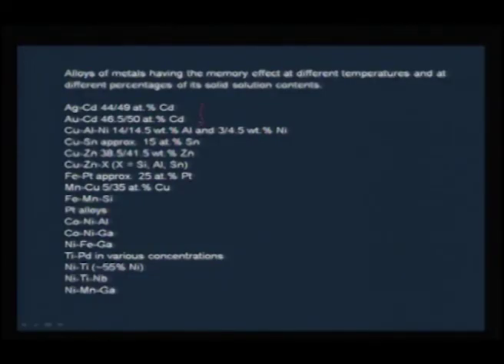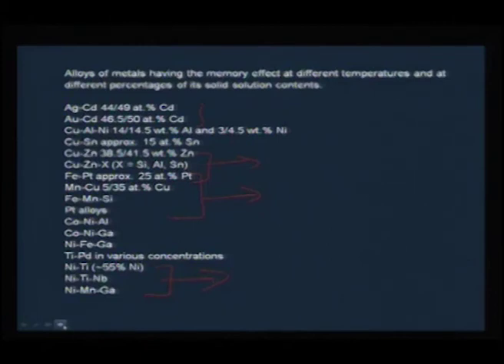Some show only one way, some show two way shape memory effect. So, we have a list of alloys which have been used. In the initial days of discovery, actually in the previous century, it was silver and gold based ones which have shown such a shape memory effect. But what we see now is predominantly the titanium nickel based one, which is nitinol, and the copper based ones and the iron based compounds. So, these have taken more limelight in the recent past because of their extraordinary stress strain characteristics, and also the way you can maneuver or make different value added products out of these alloys. I will show some of the examples in this talk.